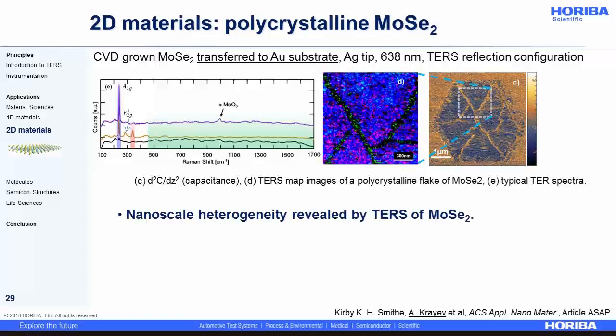The TERS map has been done in the white box that you can see on the capacitance image. So on the left, some typical tip-enhanced Raman spectra from this near-field chemical map representing the intensity of the 240 cm^-1 peak in blue and the 340 cm^-1 Raman band in red. The latter has never been reported in the literature so far. So that's anyway a first and clear indication of nanoscale heterogeneity of this molybdenum diselenide flake. I mean, all the red, pink, tiny areas that you can see in the TERS map link to the presence of this Raman band at 340 cm^-1.